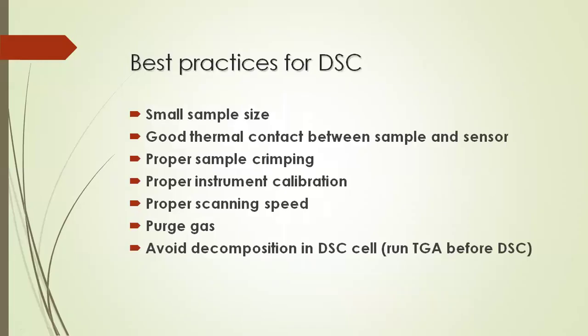Okay. Best practices for DSC: small sample size, good thermal contact between sample and sensor, proper sample crimping, so there is no thermal lag. Proper instrument calibration, so there is no temperature shift. Proper scanning speed, because the higher the rate, the higher the melting temperature and the higher the crystallization temperature. Purge gas should be inert. It should not react with your material. Avoid decomposition. Always run TGA before DSC. Otherwise, your DSC sensor will get spoiled and will cost around maybe 8 or 10 times.